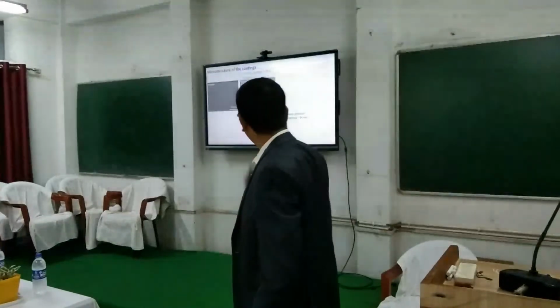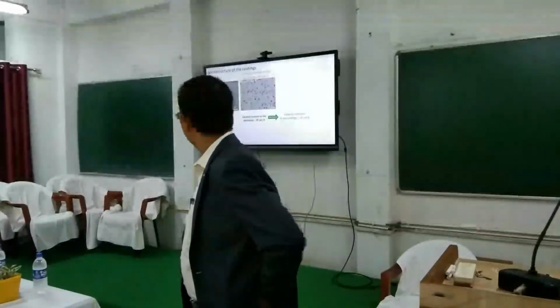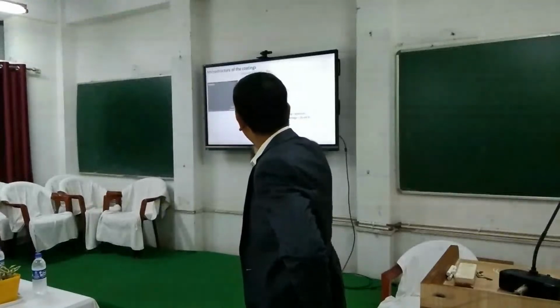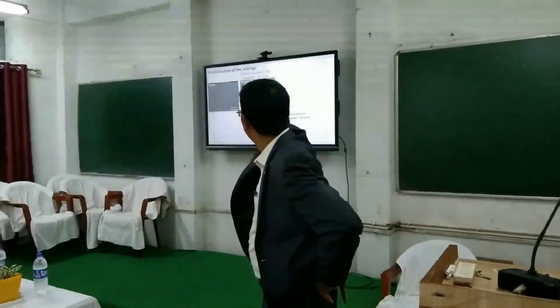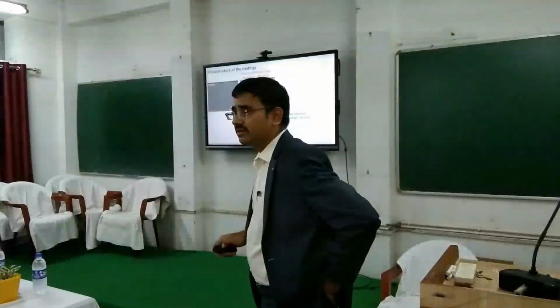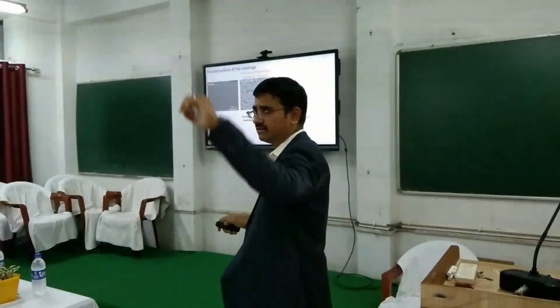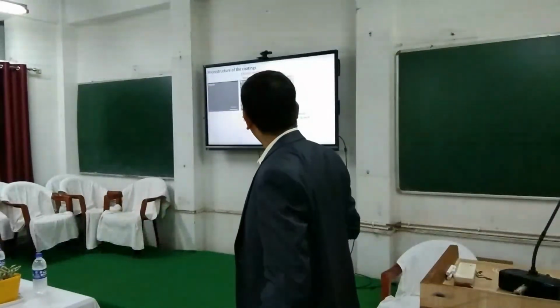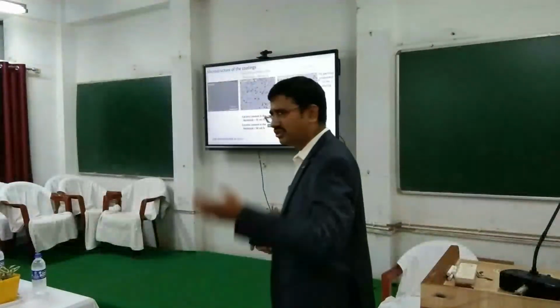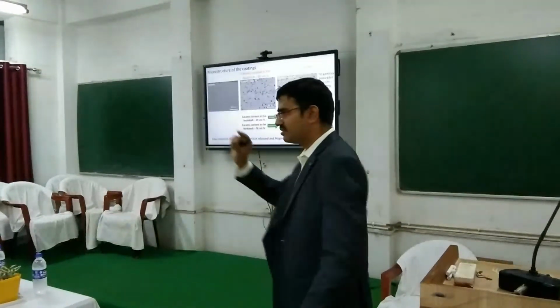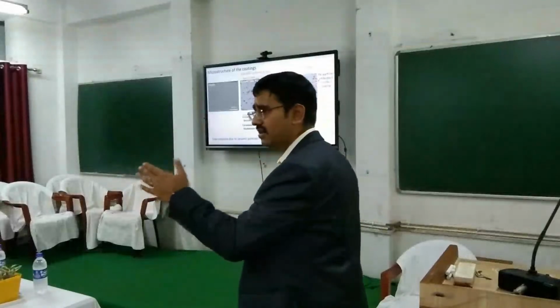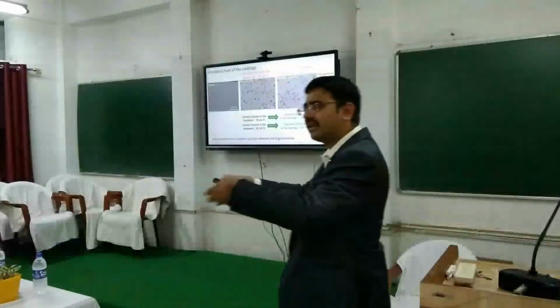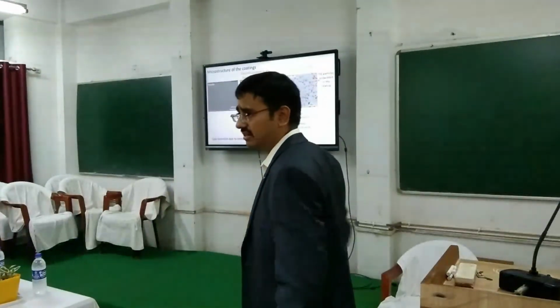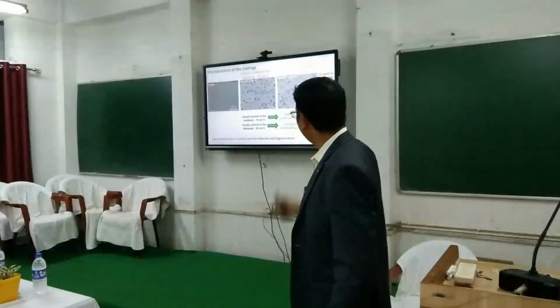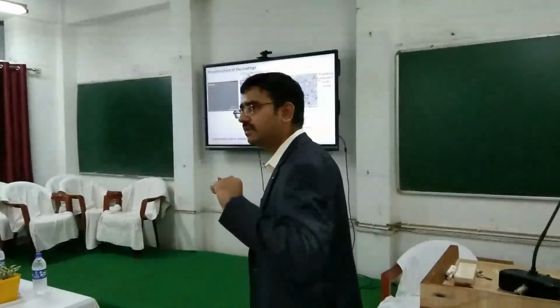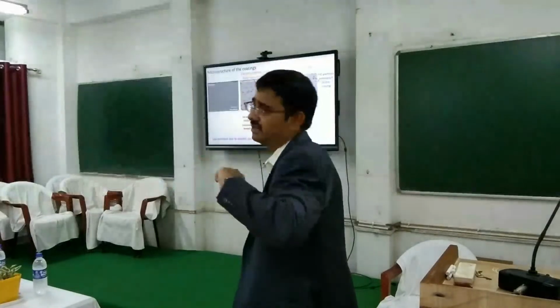This was titanium 64. You can see we could fabricate a metal matrix composite where we had the round particles and fragments embedded inside the coating. So it is like a cake. It's a softer matrix but with hard particles inside. And we could see that some particles had actually broken, and some particles could still retain their morphology, because when it impacts, some particles hit and try to break because of their brittle nature. It's evident in the case of brittle materials, but we could retain about 23% of maximum carbide particles inside our matrix.